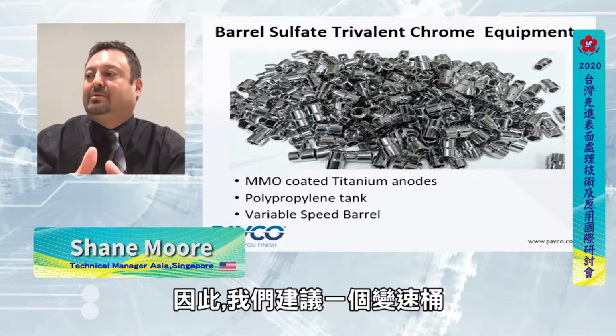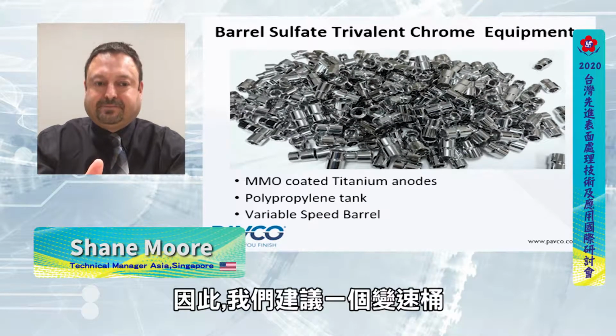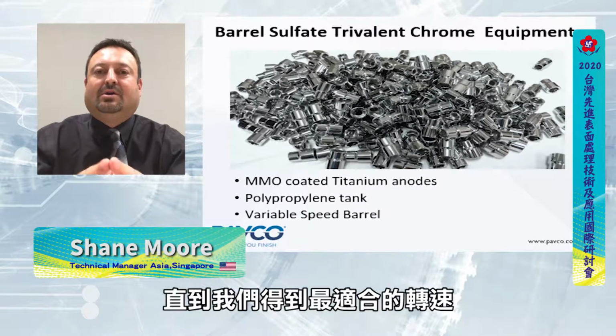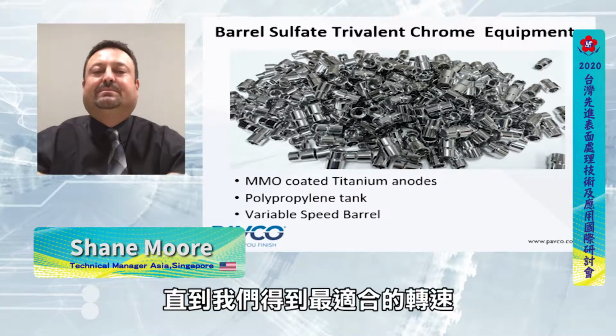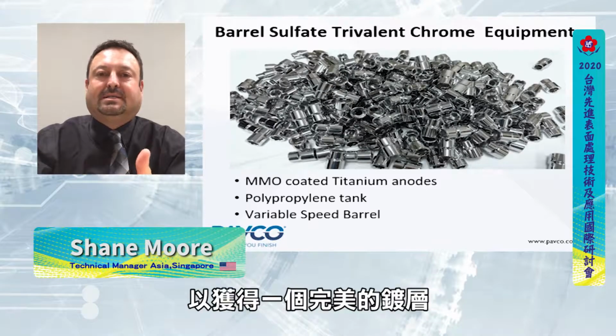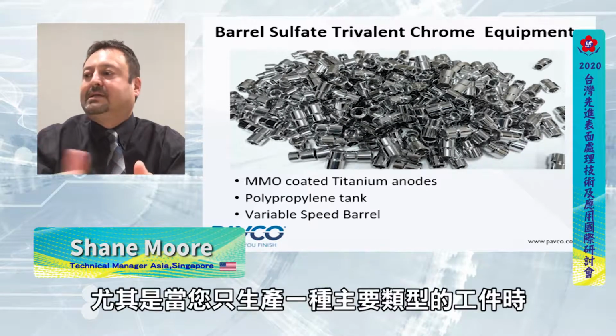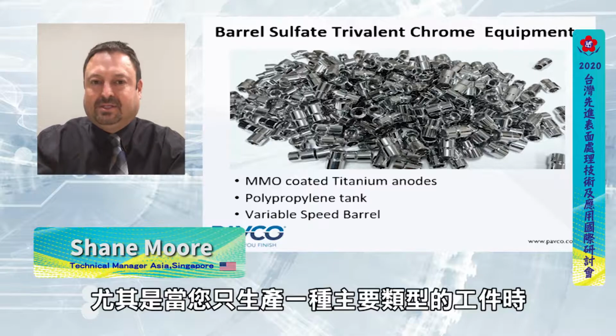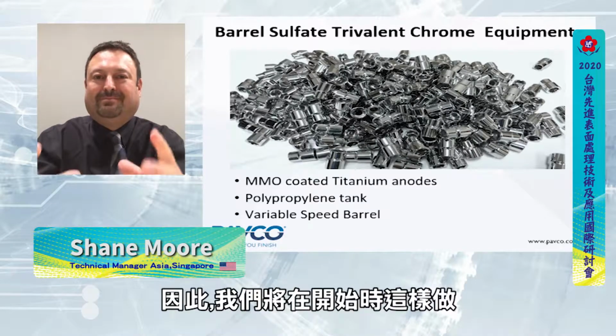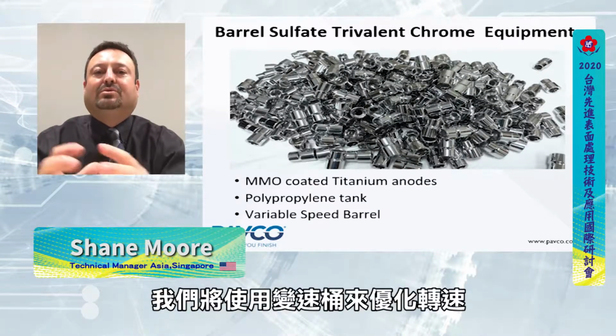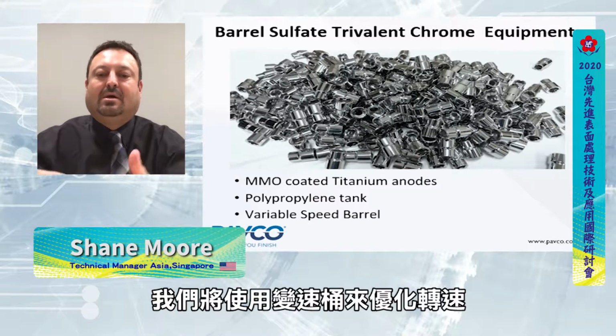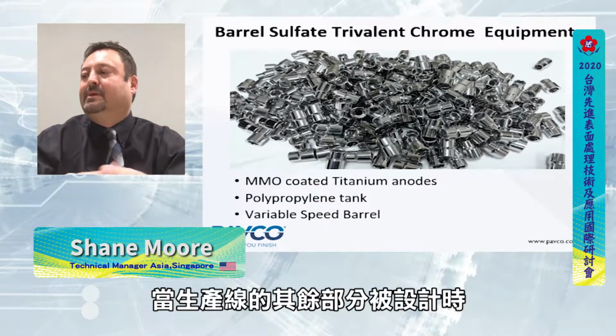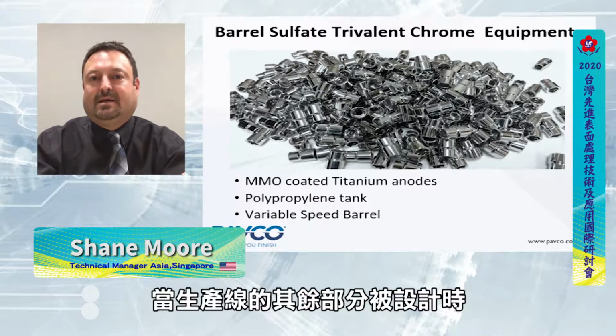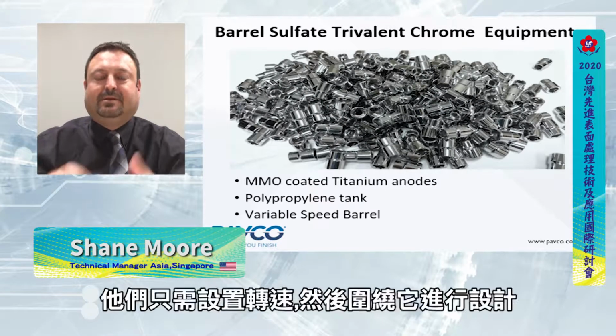So usually we'll recommend a variable speed barrel just until we optimize the revolutions per minute and get a successful deposit. Like I said, usually we'll do that just in the beginning, especially if you're only going to be running one main type of part. Then we'll use the variable speed barrel just to optimize the RPM, and when the rest of the line is designed, they don't have to have the adjustment. They can just be set to that RPM and engineered around that.